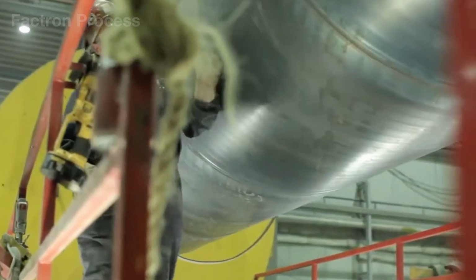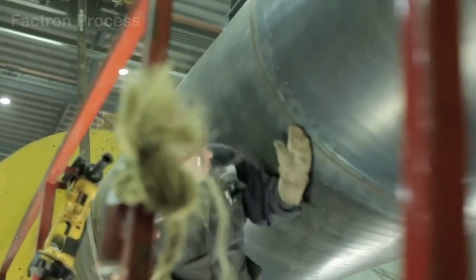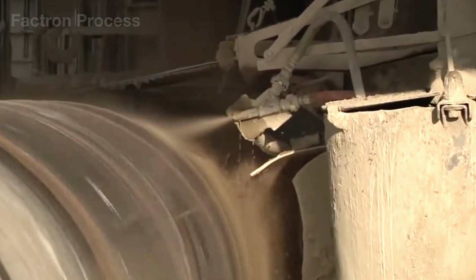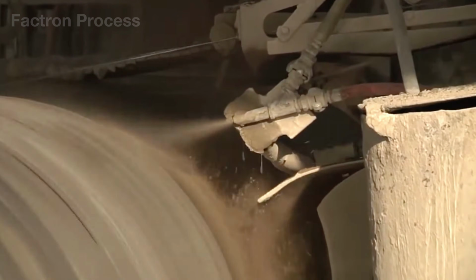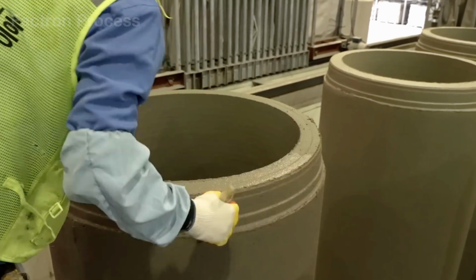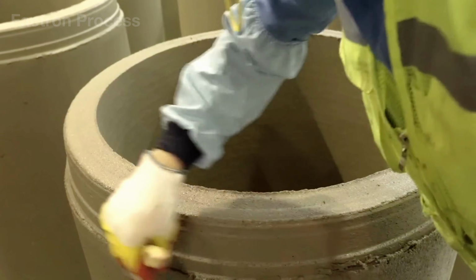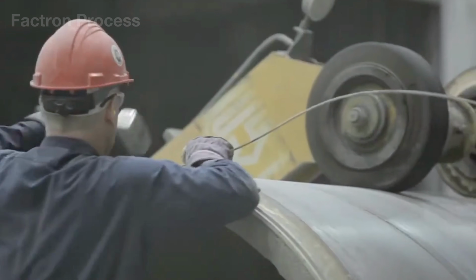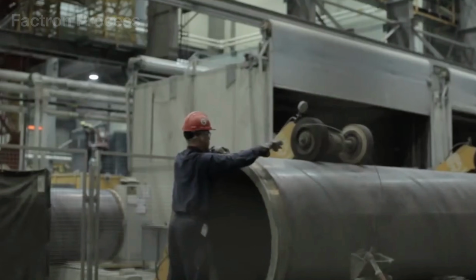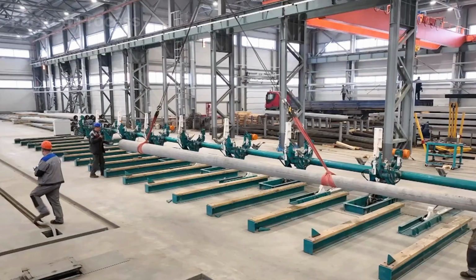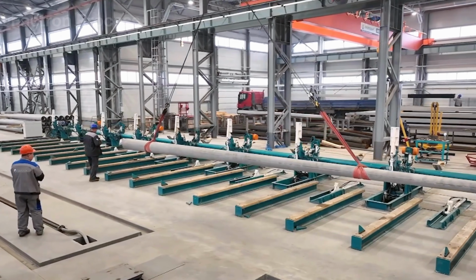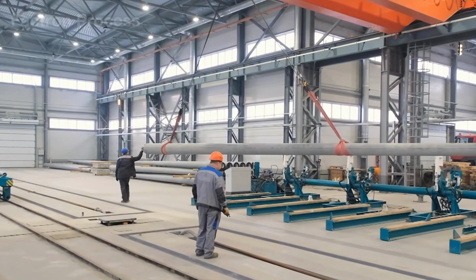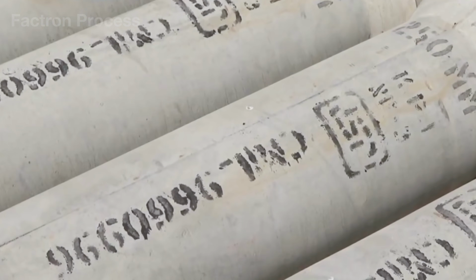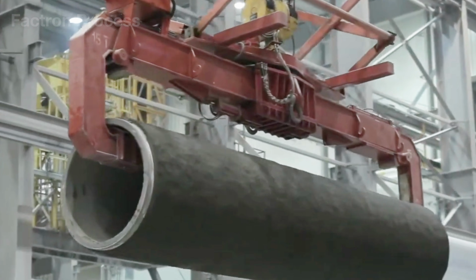After that, selected samples are placed into a 3-edge bearing test machine. A steel beam gradually presses down, forcing a 36-inch wide, 8-foot-long Class 3 pipe to withstand a load of up to about 32,400 pounds. Technicians monitor the first 0.01-inch crack to evaluate how the structure responds under extreme pressure. After passing the final test, each pipe is marked with its size, load class, and batch code before a crane moves it to the finished product yard.